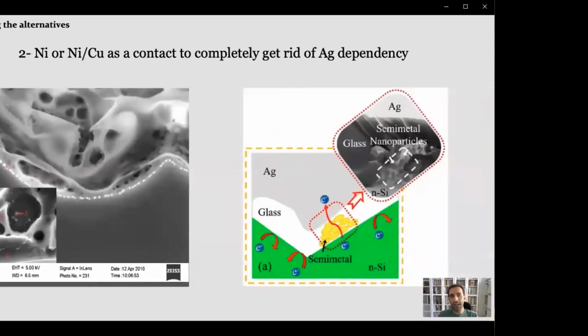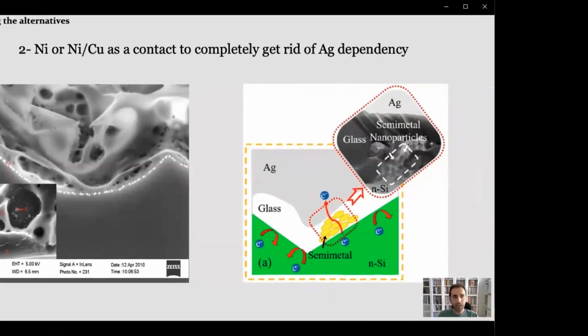But there's also an anti-hypothesis that the glass layer might include some semi-metal nanoparticles that you see in the scheme, that can make this residual glass layer obsolete and acts as a transition layer for thermionic current flow. So it cannot be acting as a passivating layer when we talk about the energy band diagram.